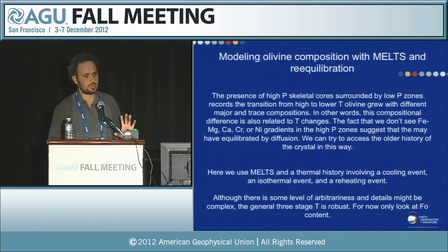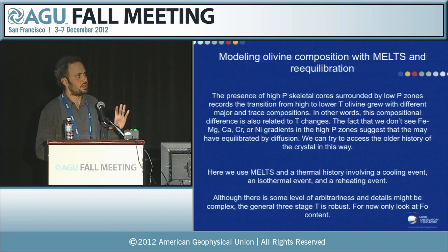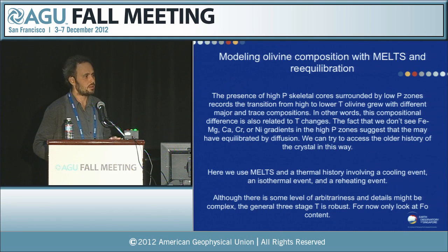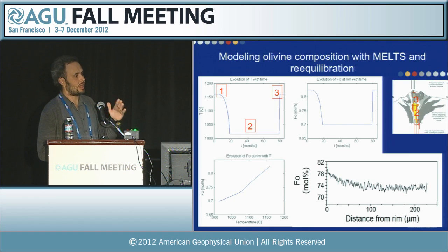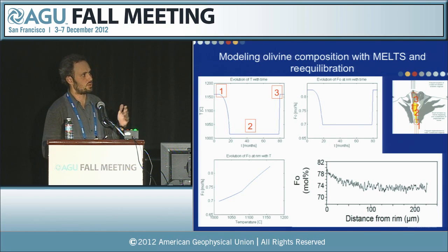So now I want to make a little bit of a transition. This is what happens with the disequilibrium model. But if we think of the context, you have this magma with this high temperature, it arrives, it quenches, and then the growth rate decreases. And because the forsterite content is also changing, it implies that the high temperature, high phosphorus part grew from a melt which was more mafic, so the forsterite would have been higher. We will look into this by using MELTS. We've taken MELTS, calculated the liquidus for these rocks, and calculated the compositions of the olivine in equilibrium with these magmas. From there we have a temperature-olivine plot, and we can assume a given time and temperature evolution and see if this fits what we have been doing.